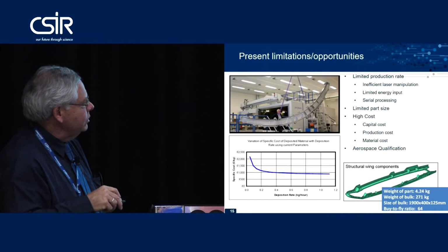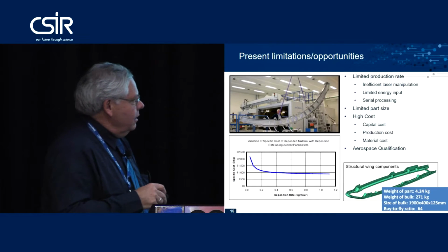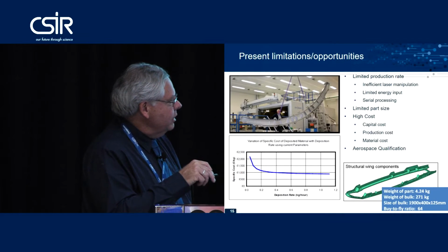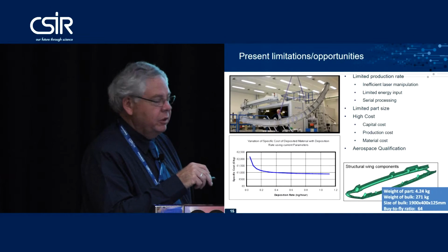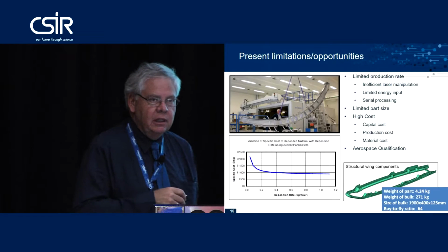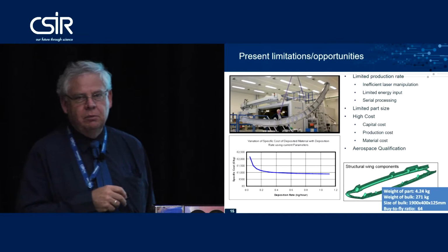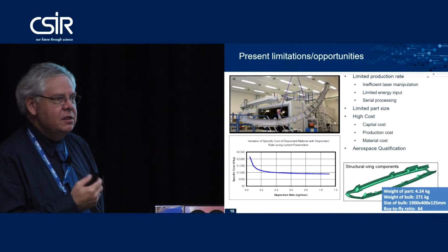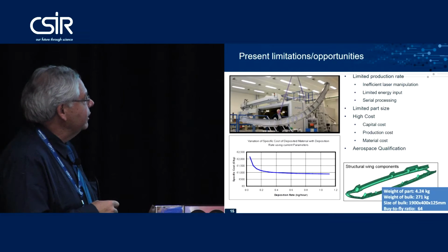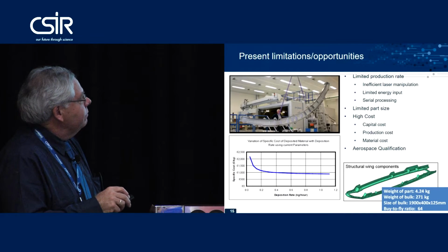Similar to this component we see here at the bottom, which is actually the wingtip of an A400M. The weight of this part is about 4.2 kilos. The bulk material, and this is actually aluminium, not titanium, is 270 kilos. So you actually mill away most of that block to produce that part. And this is a very good candidate again for additive manufacturing.